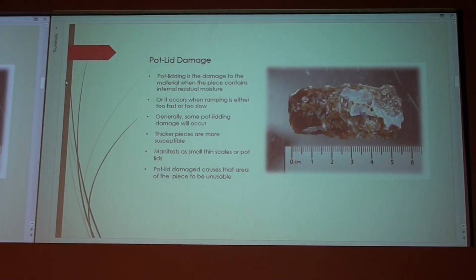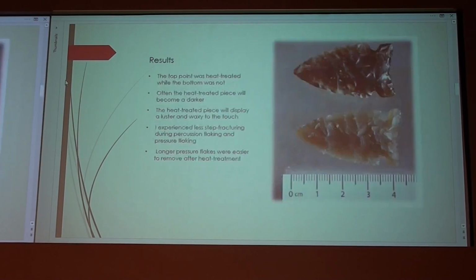Here's pot lid damage. I don't know if you can see that very well, but that makes it pretty much useless. It occurs from ramping either too fast or too slow. Generally, some pot lidding damage will occur no matter what you do. Thicker pieces are more susceptible. It manifests in small scales, pot lids. Damaged areas are totally unusable. And again, it happens no matter what you do.